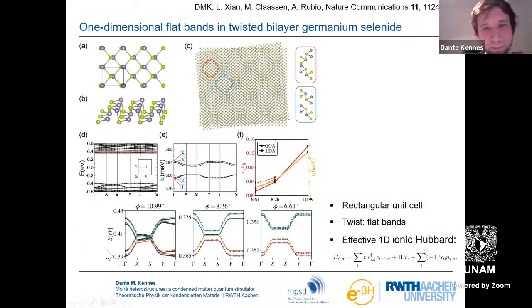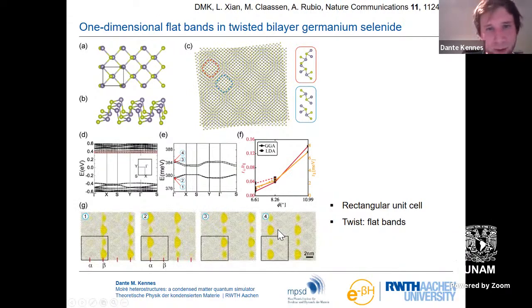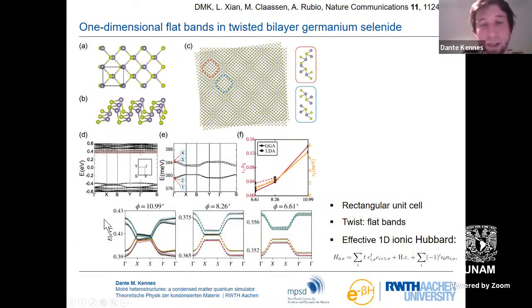All right, so to quantify this a bit more, we looked at small twist angles and we fitted this almost one-dimensional band to get the kinetic energy scales within the T parallel direction, the direction of the chain. And what we have also seen, and this is important for modeling this correctly, is two features. There's this one-dimensional band, but there's also a gap opening up between the upper and lower band here. And then also there is a sequence of charge puddles where you have a big puddle, a small puddle, a big puddle, a small puddle. And this is telling you that the effective low energy model that you're realizing is not only a model where electrons hop along the one-dimensional chain, but you also have a staggered on-site potential term, which will favor some of the sites over the others. That's why you get small puddles and big puddles.